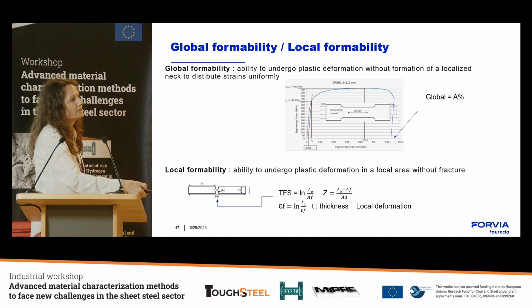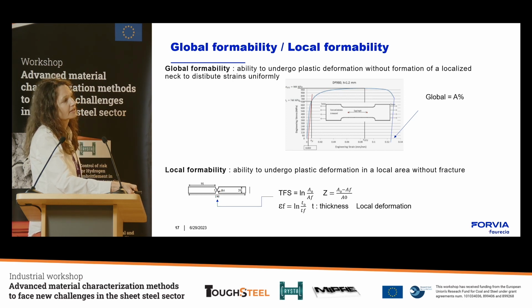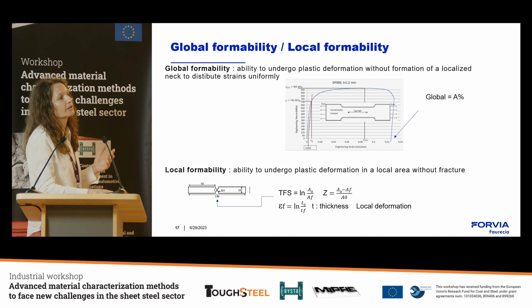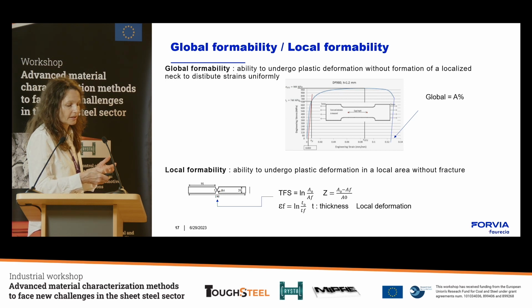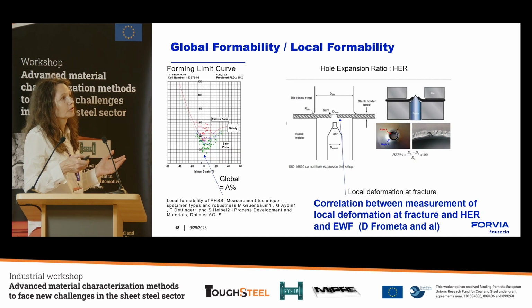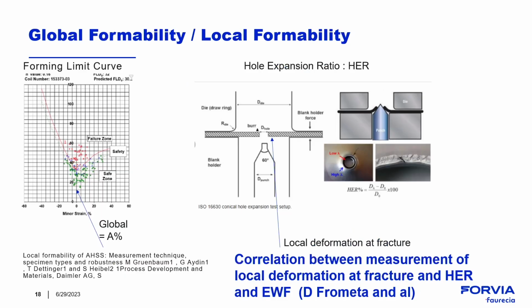Yes, and so the local formability can only be, in fact, investigated by such testing samples. And it's really an important result to get, in fact, the stress under local concentration. Currently, for the forming limit curve, there are some studies that have already been launched. For instance, there are articles from Daimler that show, in fact, that the minimum of the forming limit curve just gives a correlation with the global formability.